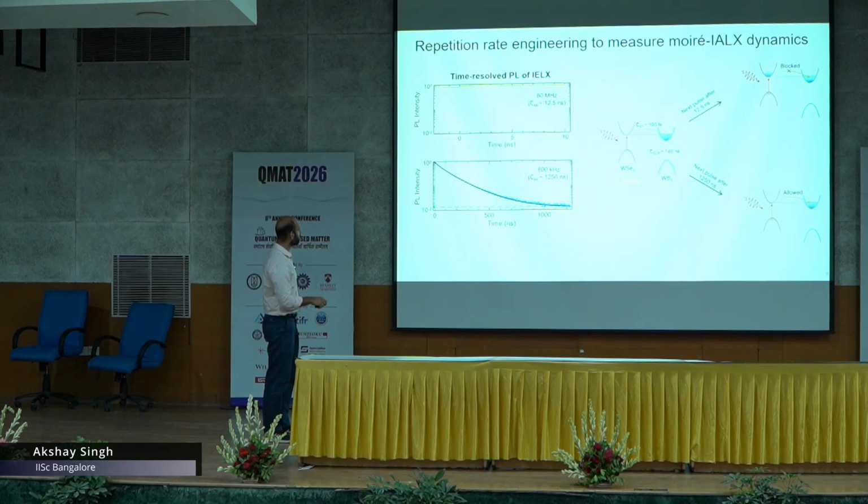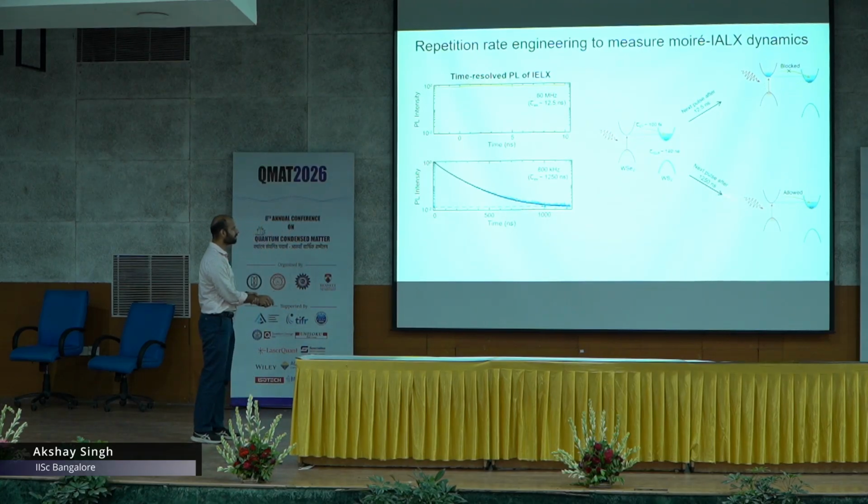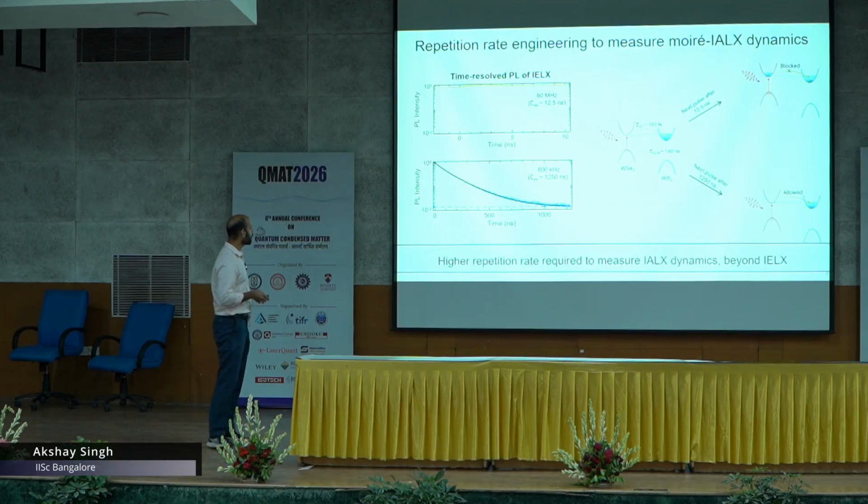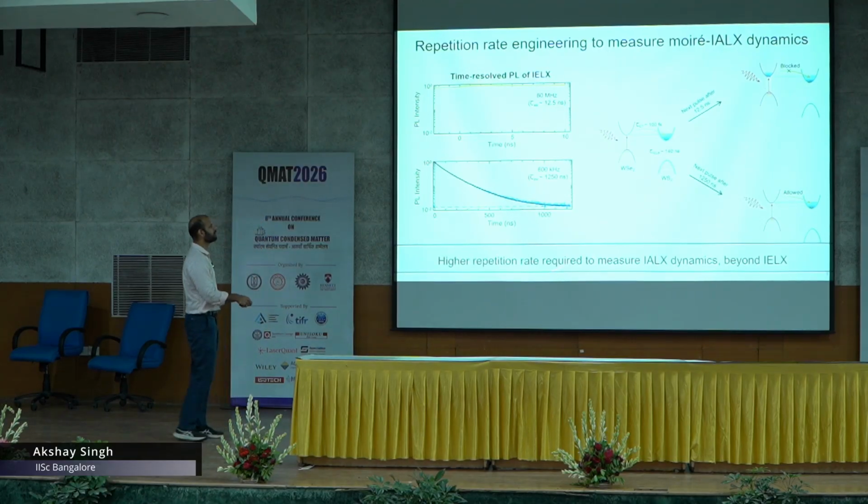However, if, for example, like in this system, we allow the system to relax between the two pulses, then we are able to measure the intrinsic lifetimes. But in this case, we will not be able to measure the intralayer excitons. So this is the crucial part. This is the reason why we are able to do all this physics. So the one sentence summary for this is: a higher repetition rate is required to measure IALX dynamics beyond this charge transfer to IELX.